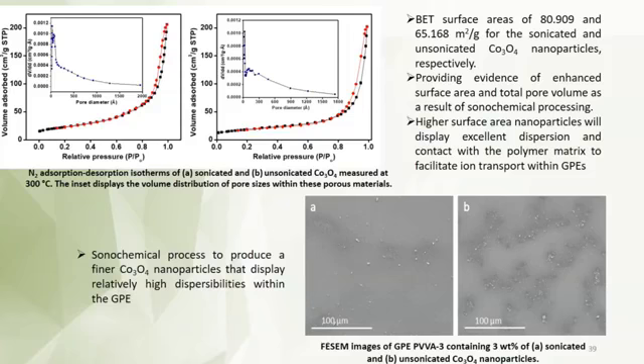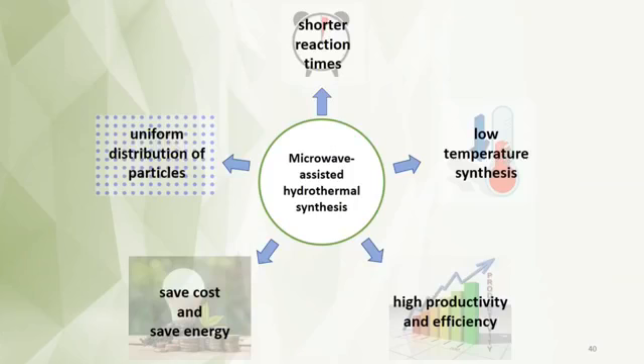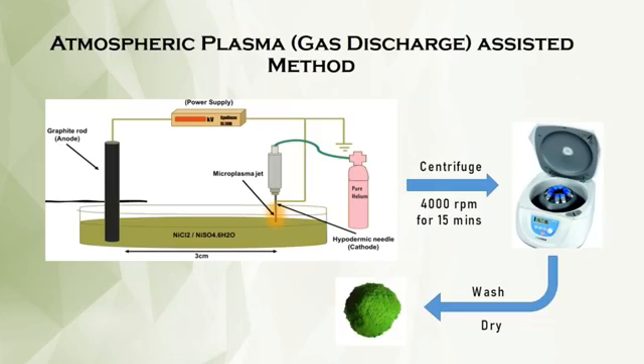The FESEM images show that the sonochemical process produces finer cobalt oxide nanoparticles that display relatively high dispersibility within the gel polymer electrolytes. And the other methods that we can use to produce the nanoparticles to be used in electrode materials are microwave-assisted hydrothermal synthesis. The beauty of this one is not only the high productivity and efficiency, but also the shorter reaction time. Okay, recently we are also working with the atmospheric plasma method to produce nanomaterials for electrode components.